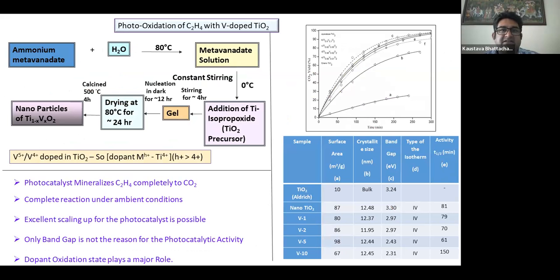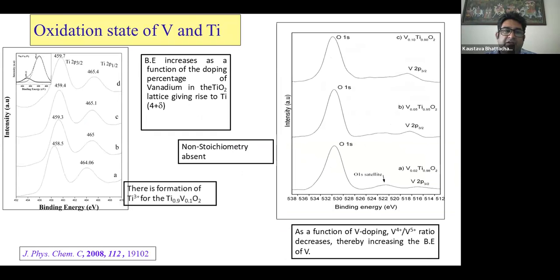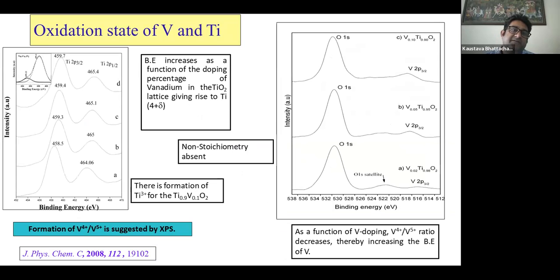We tried another system, an oxidation system. Here we have doped vanadium in the titanium system, and we have tried to oxidize ethylene. What we find is that up to 5% doping of vanadium, titanium is present in the +4 state. But if we dope more than 5.8% of vanadium, we find that titanium is present in both +3 and +4. Vanadium is basically present in two oxidation states, +5 and +4. If the amount of vanadium 5+ increases, then to maintain the lattice charge, more titanium 3+ is produced in the structure. Now, if it is an oxidation process, titanium +3 eats away the holes very fast and reduces the reaction. So we can prove directly that if there is a formation of titanium 3+ structurally, that reduces its photocatalytic efficiency.